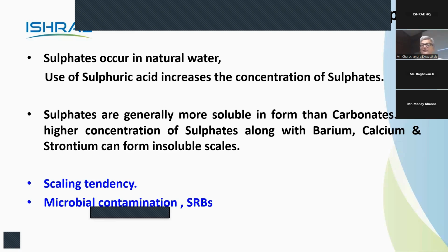Sulfates are more soluble than the carbonates, and basically they don't appear as scales in the circuit, but they can form very insoluble hard scales when they come into contact with other cations like barium, calcium, strontium, etc. So sulfates have a scaling tendency, and there is also microbial contamination, like sulfate reducing bacteria.